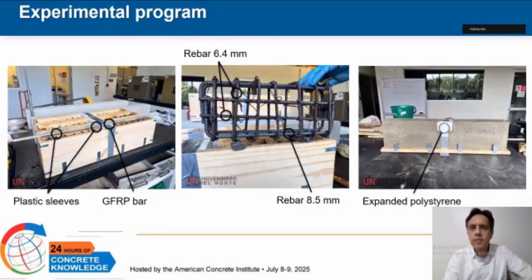The second image shows the steel reinforcement cage used to simulate confinement. It contains 6.4 and 8.5 mm diameter rebars that are placed strategically to replicate the presence of transverse reinforcement and the shear effects observed in real structural elements. The third image displays the expanded polystyrene inserts used to form the central hinge. This feature ensures a clean fracture plane and consistent bending behavior during testing. All specimens follow this setup to maintain experimental consistency and simulate service-like stress conditions.